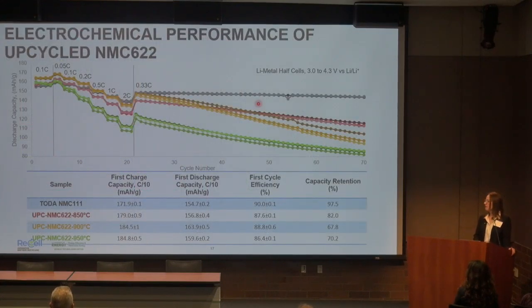But even though we have this observation that we have a homogeneous cathode material at this higher nickel content, we are increasing our initial capacity from 155 to 164 milliamp hours per gram, but we're still not getting the density gains that we would expect for a bulk, higher nickel cathode composition.